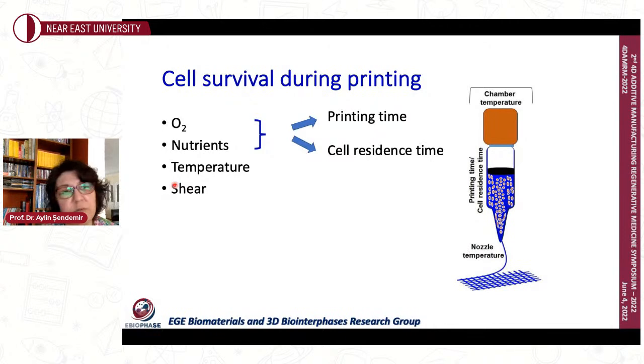Usually this factor is commonly overlooked, but no matter what type of printer we're using, during the injection, or even in the inkjet or laser printers, during the printing process, the ink is subject to quite a lot of shear stress. And this shear stress can affect cellular viability tremendously. So keeping the chamber temperature high or using a lot of shear during printing, you can get a stable structure, but you might possibly lose most of your cells during printing.